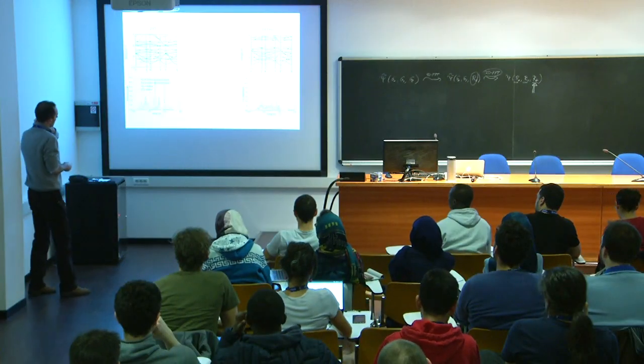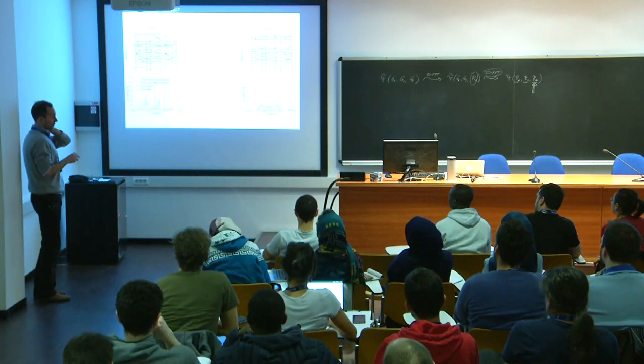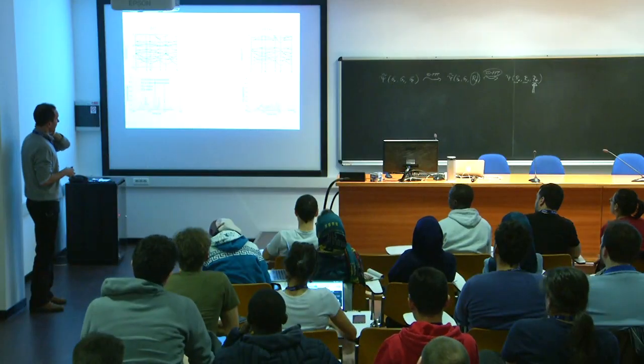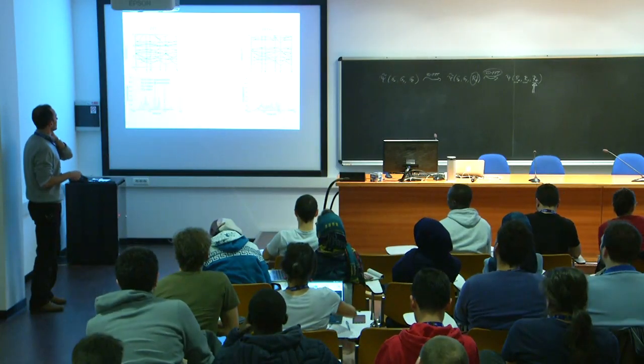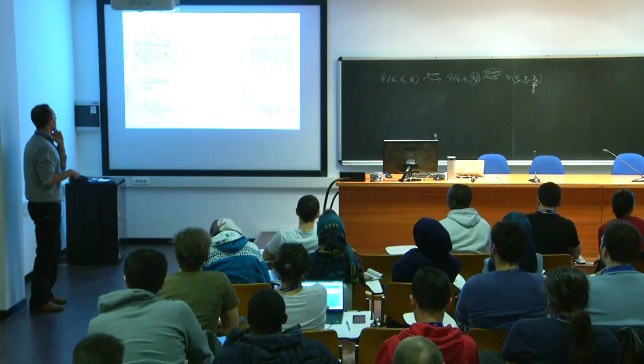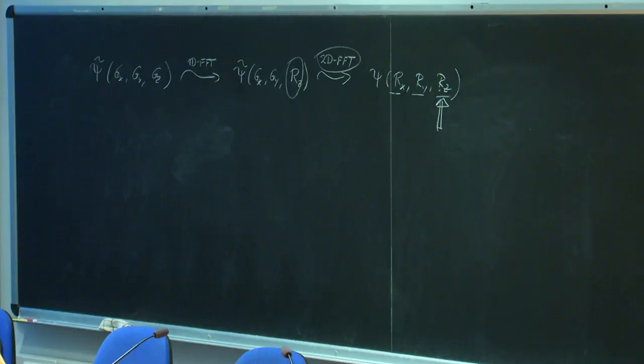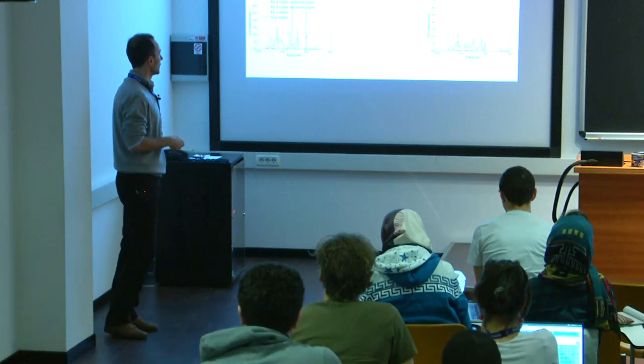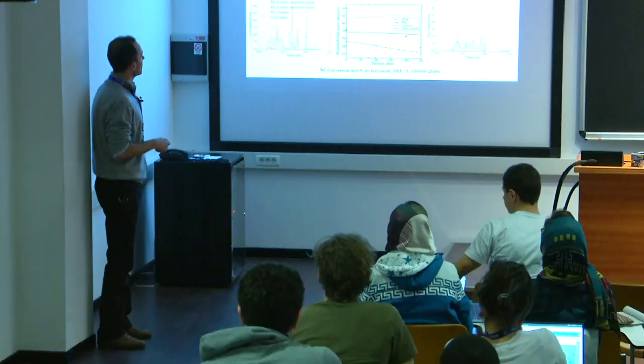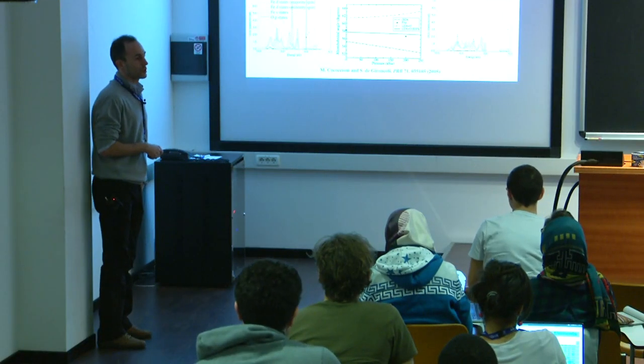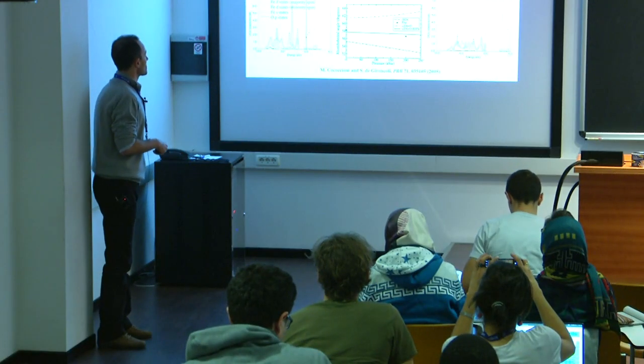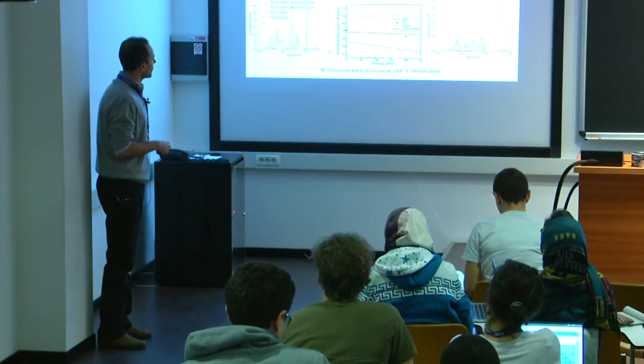Okay, the iron oxide deserves some attention because it's significant regarding the symmetry problem. If you apply DFT+U, you remember we got the metallic ground state, which we were not happy about because it's known to be an insulator. However, if you apply the U correction, you get a gap, and you might be happy about that because you got an insulating ground state and maybe you expect the properties to be right. And in fact, some properties do turn out right, like the insulating character and the antiferromagnetic ground state, which you can now stabilize. And you might also get the rhombohedral distortion.